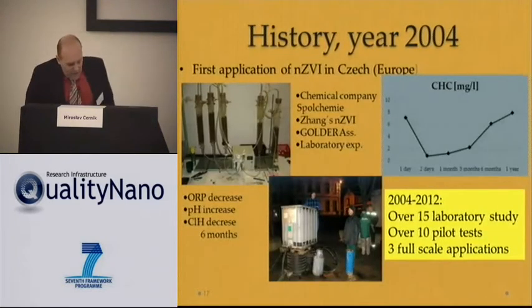But my talk is about the application mainly, so we started in 2004, where we did the first application outside of the United States, and we did some very old-fashioned laboratory experiments at the time, and then we did some simple application of the particles which we got from Golder Associates and particles according to Professor Zhang's recipe. And we saw that we are able to reduce the concentration of chlorinated ethenes for at least 6 months.